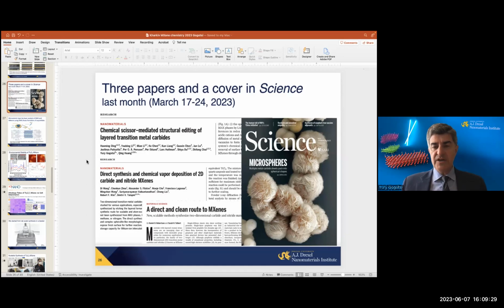People demonstrated growth of 2-nanometer-thin molybdenum carbide and several other carbides. But you cannot technically call them MXene because no one has come up with a self-terminating method of synthesis. What it means is that they can grow 2 layers, 3, 4, 5 in an uncontrolled way. But in my personal opinion, it's just a matter of putting in effort. It looks today absolutely obvious.